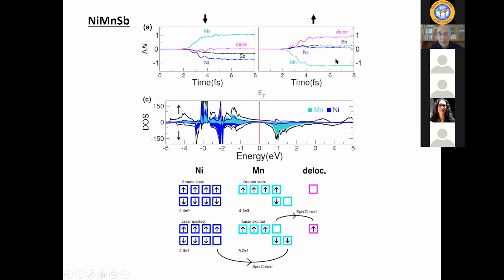Okay, so in the very simplified picture that is depicted down here, you see exactly that. This is the initial configuration of nickel. There's very little magnetization, it's been saturated. And then with the laser, you induce a transition of a downspin from nickel to manganese. And you also induce on manganese, where the main magnetization initially is, a transition of an upspin to the interstitial region.